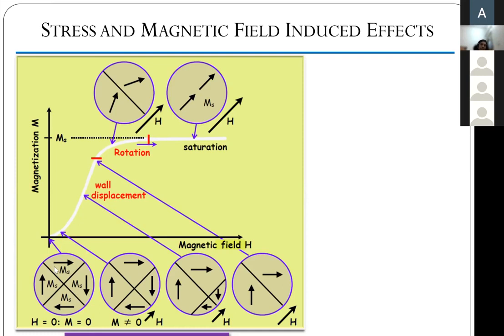Now we keep on increasing the magnetic field, slowly increasing it in a chosen direction. As one can see, the domains that are oriented favorably to the magnetic field direction, in other words, if I calculate the angle between the magnetic field and the domain, whichever ones are closest to the magnetic field orientation, will grow at the expense of others. The others, which are unfavorably oriented, will start reducing in size.